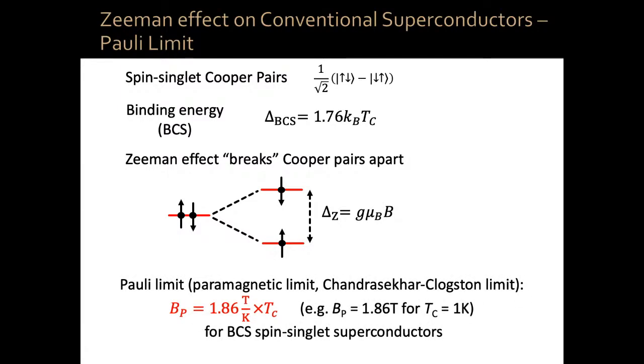That leads to this Pauli limit, also known as the paramagnetic limit, or Chandrasekhar-Clogston limit, which tells you that your critical field should be at most about 1.86 Tesla per Kelvin times Tc. So for 1 Kelvin Tc, 1.86 Tesla. Okay? And that happens for all conventional superconductors.